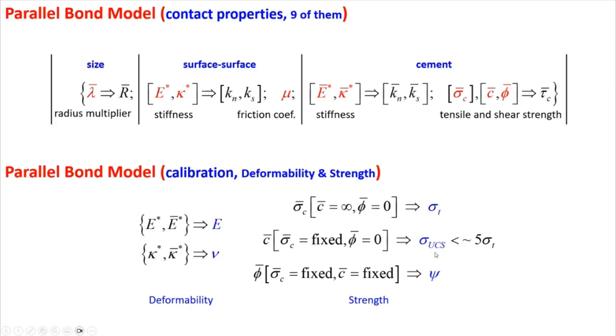And so that's going to let us control the UCS, but only to a certain extent. Because even if we have the shear strength infinite and we choose the tensile strength to match the direct tension strength, now we're done. We can't change that. We just keep it infinite. We do a UCS test, and even then it's going to fail. For a parallel bond, it's going to fail at about 5 times the tensile strength. So the only thing we can do, if we also allow it to fail in shear, is make this smaller. And certainly there are sandstones that have a UCS that's not 5 times the tensile. It might be 2 or 3. Most competent sandstones, though, don't. So that's a limitation that we have with the parallel bond.